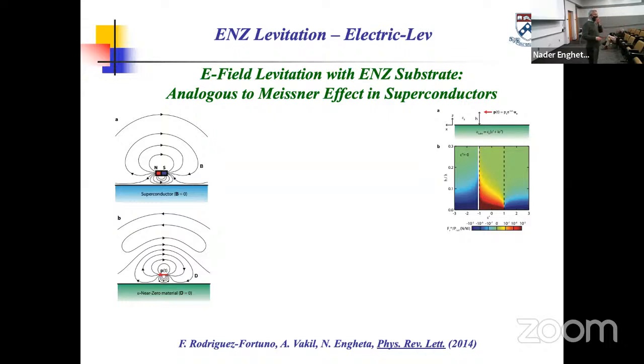So we actually found a result better than what we thought. Not only is epsilon near zero going to give us a repulsive force, but any epsilon between minus one and plus one will do the same. Now, this is for the case where the imaginary part was zero, so we assumed no loss. But we said, okay, let's introduce loss to be realistic. And when you introduce even this huge amount of loss of 0.8, you notice the phenomenon is still there. Of course, the range of the permittivity will change in order to achieve that, but it's there.